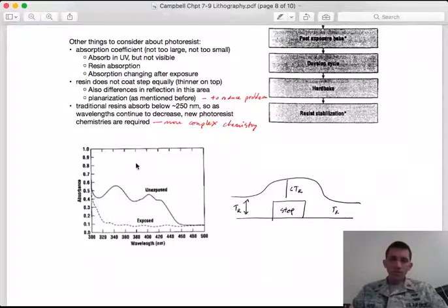And so this needs to be factored in to the process times, because you can imagine, let's say in this example, we're going from high absorption to low absorption, which means that the back half of the photoresist is going to be exposed to more and more UV radiation as the process continues, right? So it's going to be kind of accelerating that exposure process, which can have impacts on how much process time is required.